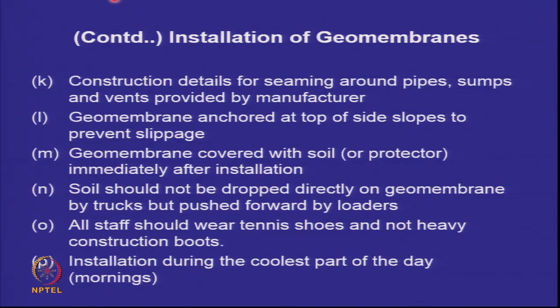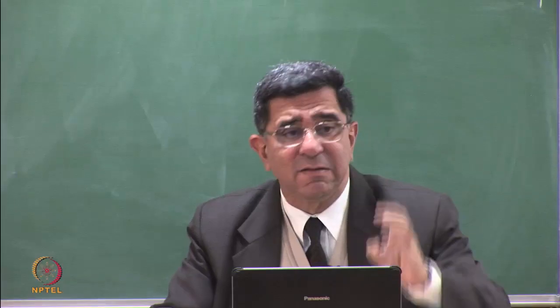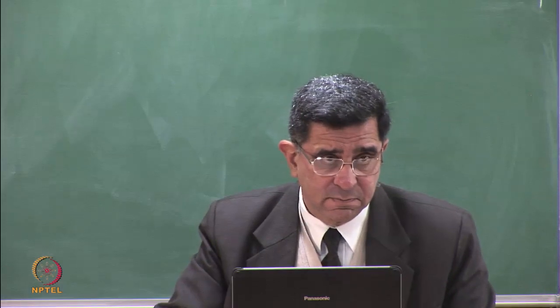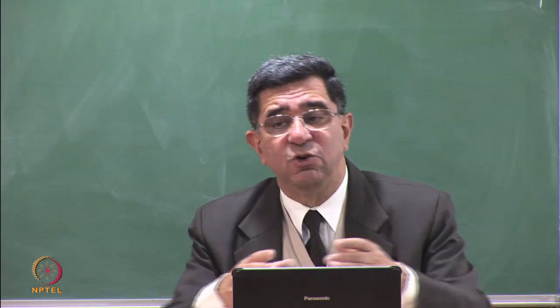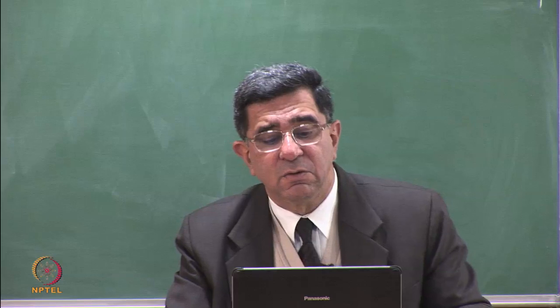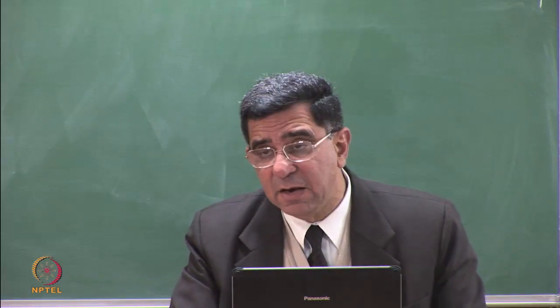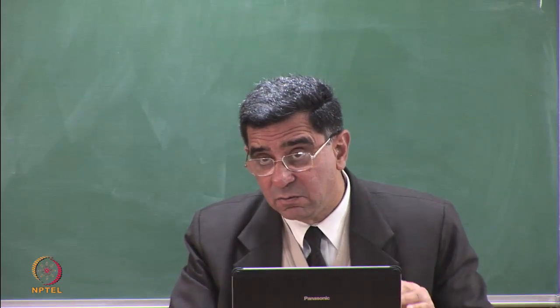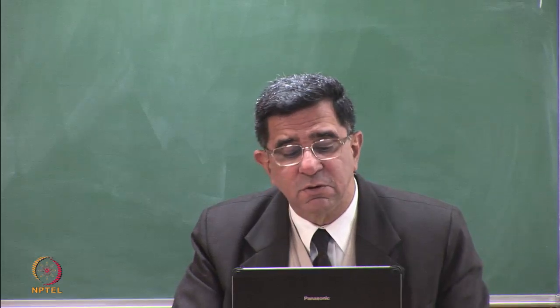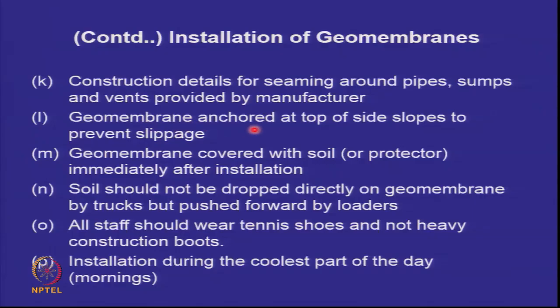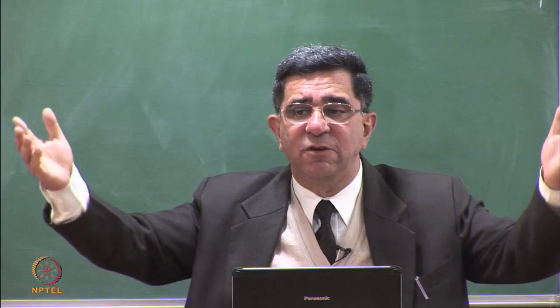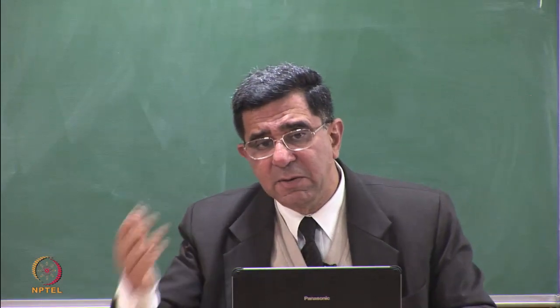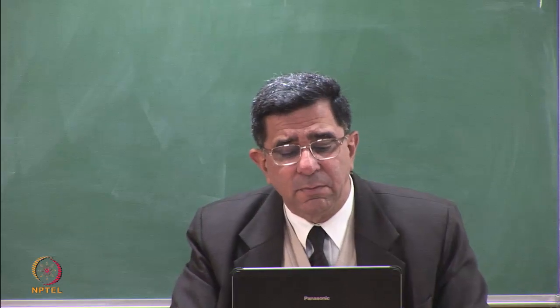Very important is there will be some pipes which will be passing through the geomembrane. And that, how do you weld the geomembrane to the pipe? Those construction details have to be given by the manufacturer and have to be with strict quality control, they have to be ensured. Geomembranes are anchored at the top of side slopes. If you put a geomembrane on a side slope, it tends to slip down. So there will be an anchorage in a trench at the top.